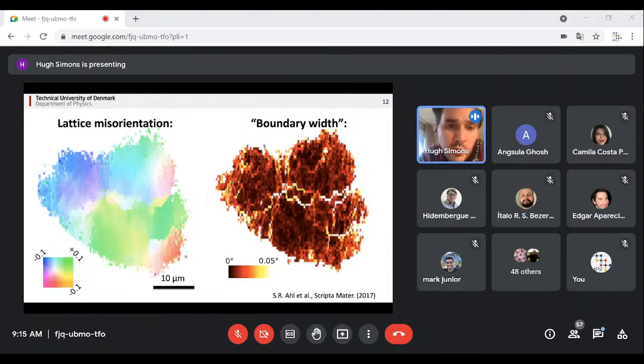What we learned from this is that if you look very carefully, you can see the boundaries between the subgrains are associated with some kind of retrusions, some indentations in the sides of the grains. This corresponds to the grain growth being inhibited by the intersection of the grains with these subgrain boundaries. So essentially what's happening is the grain boundaries and the subgrain boundaries are pinning themselves, and they're preventing further growth. And this turns out to be exactly the mechanism that we're observing for this unusual and unpredictable subgrain growth within these materials.